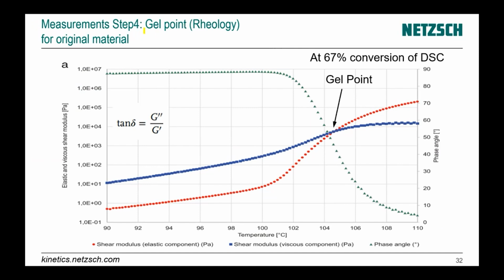But for this case, it is necessary to have a gelation, gel point. We made rheological measurements with an oscillating parameter, and we found a gel point during the heating. This heating was done with 3 K per minute. And then we compare this data with DSC data with the same heating rate.